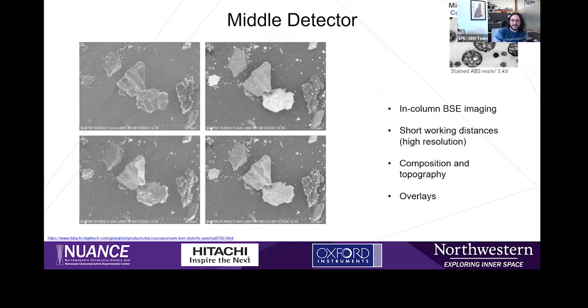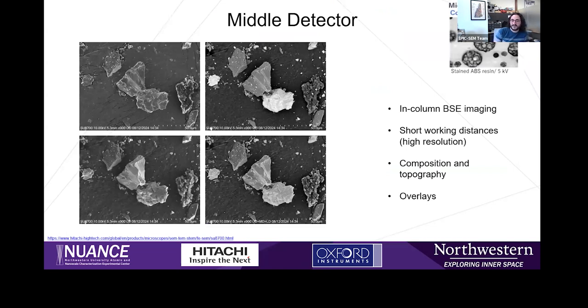So first we'll take a quick look at the middle detector. The middle detector is a really great tool to have on the 8700. It offers in-column BSE imaging, which is really useful on a high-resolution microscope because it allows you to work at very short working distances. Typically, BSE detectors that sit underneath the objective lens usually require a working distance of a minimum of 8 to 10 millimeters or so to optimize that backscatter signal. But you can see from the top right image, we're able to sit at around 5 millimeters working distance for our backscatter analysis, which is really going to help our resolution, and we're still getting good backscatter contrast there.